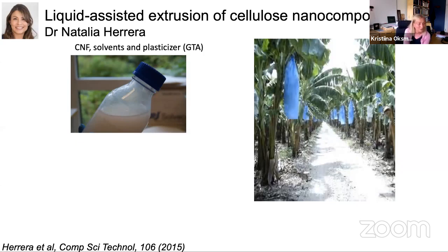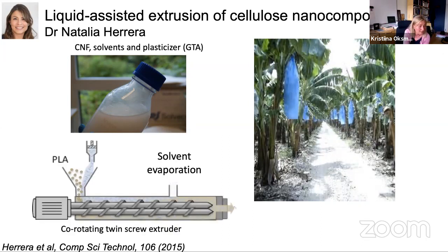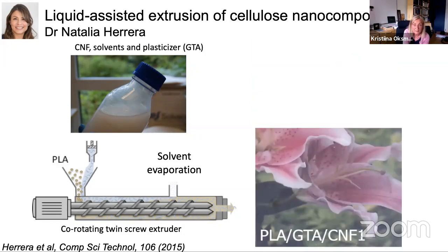Here we used also cellulose nanofibers, and these nanofibers were also from a residue source. They were from this banana residue, and we mixed those with water and also with solvent and plasticizer. And this plasticizer was used to try to make the PLA softer. This suspension was fed in the extruder together with PLA, and the solvents were evaporated during the process. And we made very nice films where these nanofibers were well distributed and dispersed.